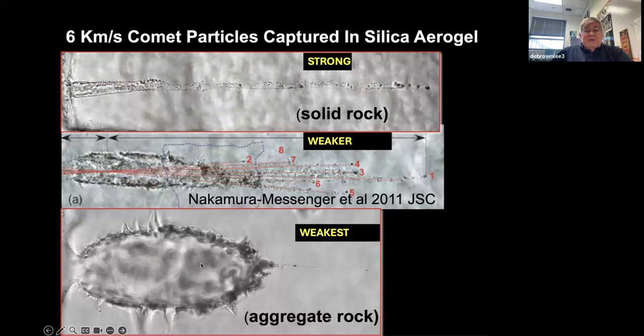Here are pictures of 3 tracks in aerogel, particle coming in from the left. The top track is what happens when you have a very strong particle that doesn't come apart. The middle track is a particle that's coming in and broken into major fragments, which are numbered on the right - this could be like a chondrule fragment that was fractured somehow, had fractures in it before it hit, and they just separated. The ram pressures on particles entering the aerogel is actually very low, so you're not having sharp, hard shock effects on the grain to fracture them.